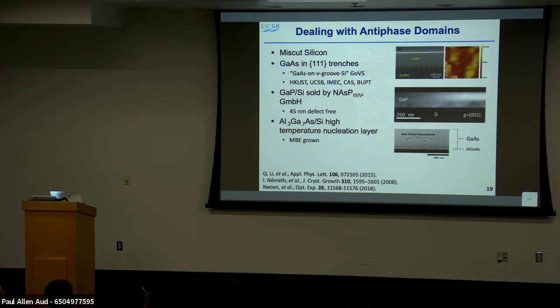The other approach is growing gallium phosphide on silicon. And so again, it's a fairly thin layer, a few hundred nanometers gallium phosphide, but you can see all the antiphase domains. They all terminate within that first couple hundred nanometers. And again, it's a process NAsP developed, and you can buy those wafers in 300 millimeter size. And the third approach that's being used is to grow aluminum gallium arsenide on top.